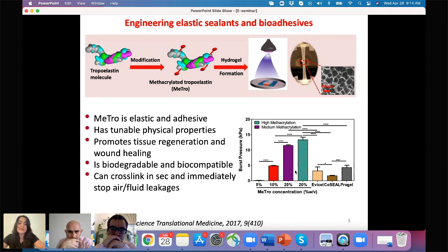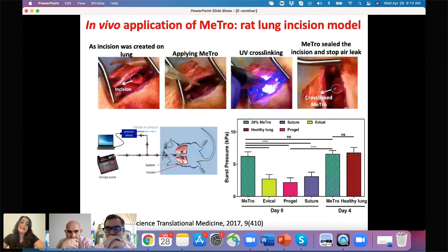Once we optimize the properties of MeTro in terms of adhesion, mechanical properties, we then test it in vivo. We always start with the small animals. Here is a rat lung incision model where we create a defect on the lung. The polymer was delivered as a solution, and then we cross-link it with light. And then here is the defect that was sealed with MeTro. And then following this, we did an in vivo test, and also after 4 days, we measured the burst pressure of the lung by using this device. We apply air inside the lung, and then we measure the burst pressure by using a sensor.